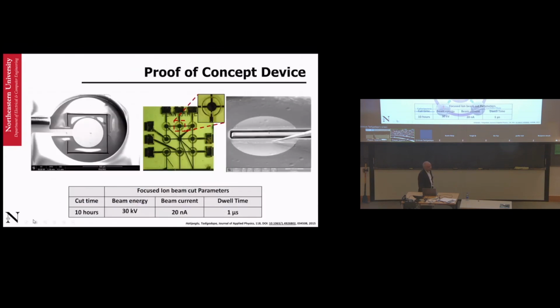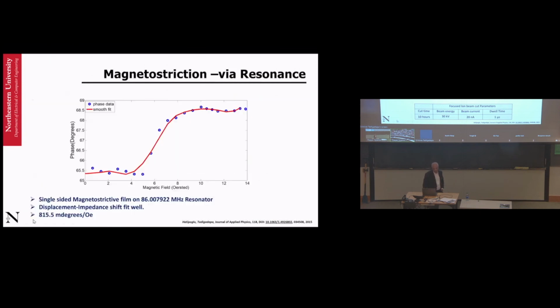And so basically what we have done here is we've taken one of those resonators, made it into a cantilever, coupled it with a magnetostrictive thin film, Metglas film. So when you apply a magnetic field, the cantilever starts to bend out of plane because of the two layers. And as it bends, it induces a strain in the quartz, which then shifts the resonance frequency, which gives you a measurement of a magnetic field. So you can take the same idea, IR sensor, biosensor, and now magnetic sensor. So this is basically coupling strain into it.